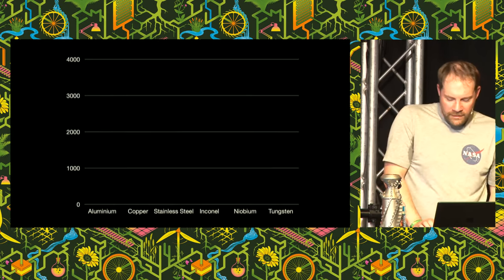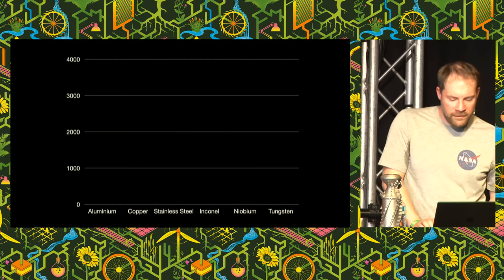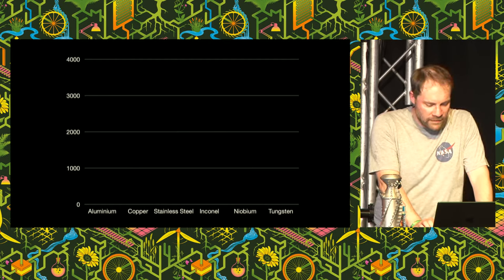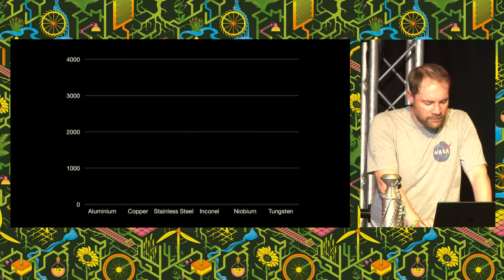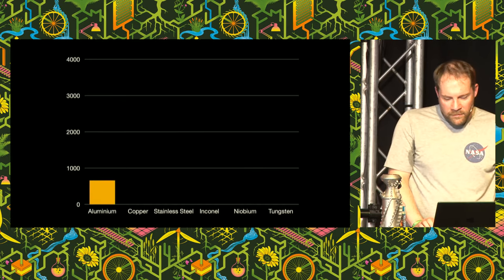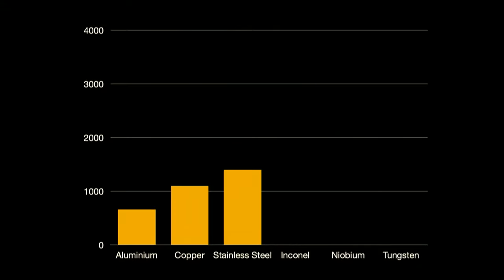So, here's a graph. On the left is temperature in degrees Celsius, and it's going to be the melting point of a bunch of different materials that we can use to make chambers out of. So aluminium melts at about 660 Celsius, copper melts at about 1,100 Celsius, stainless steel has a melting point of about 1,400 Celsius. Inconel, which is a sort of high-performance nickel alloy, slightly less at 1,350 Celsius, but it stays stronger for a much higher temperature, so we tend to rate it above stainless steel as a thing to make rocket engines out of.